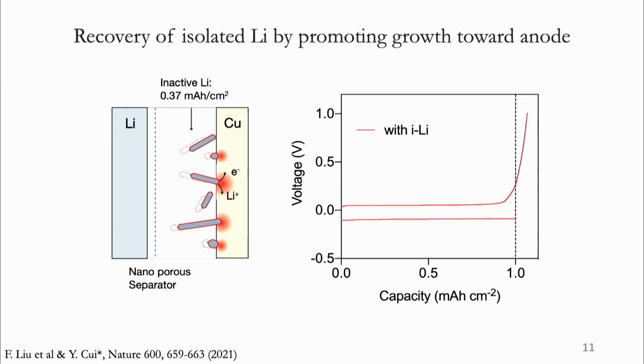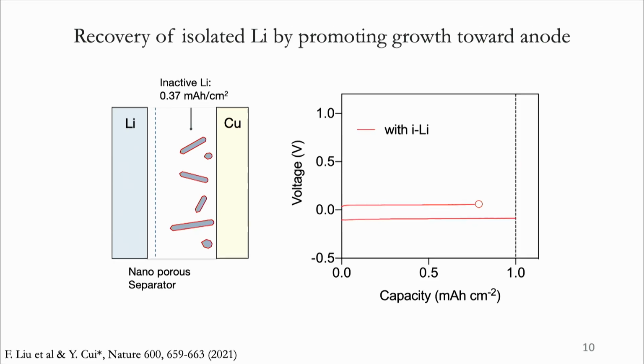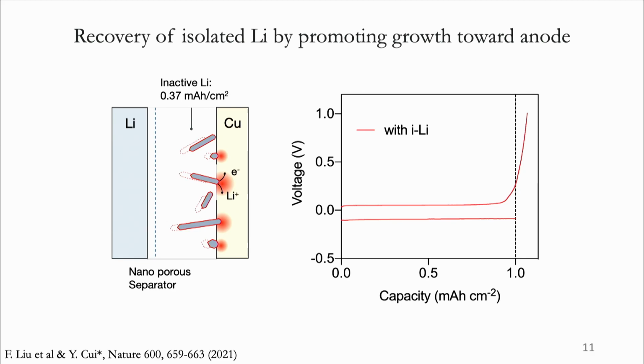Now we are gradually lowering the cell voltage, the electrochemical potential of copper, to deposit a certain amount of fresh lithium onto the substrate. And then we start to dissolve, to strip it away using an electrochemical method. But during this time, we are not only stripping away the fresh lithium we just deposited, we are also promoting the growth of isolated lithium toward the copper substrate. So that's why we're actually seeing over 100% Coulombic efficiency in this case.